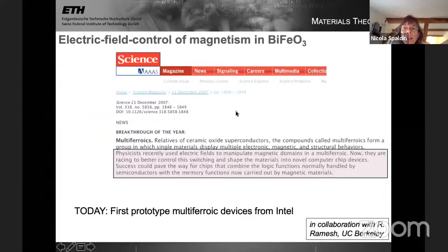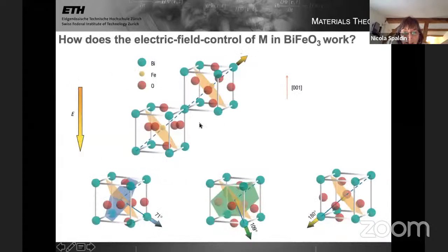Yeah, this is a very good question. You could argue, in fact, another way to think about what I was explaining here is that the coupling between the antiferromagnetism and the ferroelectricity is caused by the domain walls. It would be an alternative viewpoint, and maybe it's easy to see in this picture. When I have a ferroelectric domain, then my antiferromagnetic plane is the plane perpendicular to the polarization. And within that ferroelectric domain, you're absolutely right.